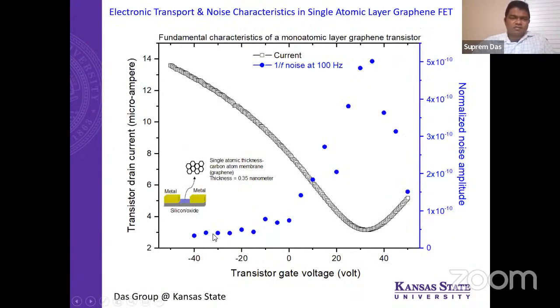So this is our very initial measurement, a beautiful noise plot. This is from a single graphene layer transistor. You can see the normalized noise amplitude, and this is your conductivity or your drain current. Wherever you have the lowest value of drain current, you have the highest noise, and that's very counterintuitive. You think that when you have higher current, you have more carriers and you'll have more noise. But in the case of graphene, it's the opposite. The lower the current, the higher the noise.